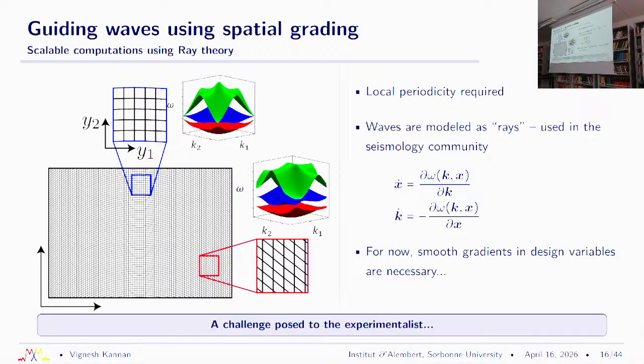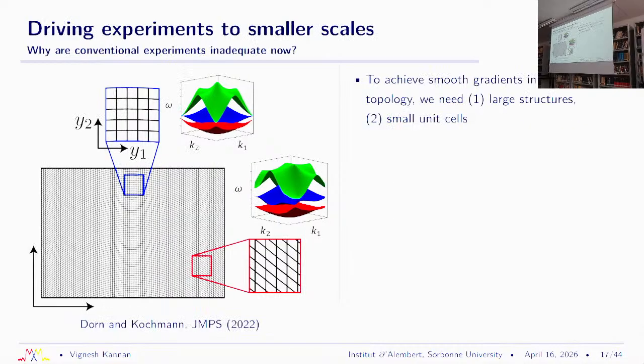And this is where he came to me and said, yeah, sure, the aluminum plates work. He actually made a reasonably fancy aluminum plate, but we soon hit limitations on how much of gradients we can achieve because you have limitations in the manufacturing capability of these systems. So the fundamental requirement here is if we want to have smooth gradients, we want small unit cells or high density of unit cells within our sample. So if I was sticking with my water jet cut aluminum plates that I showed you before, I either have to make my plates really, really large, which makes it prohibitively expensive, or I need to improve the resolution of my manufacturing process. But when I do that, I basically move away from beams because I don't have slender beams anymore.